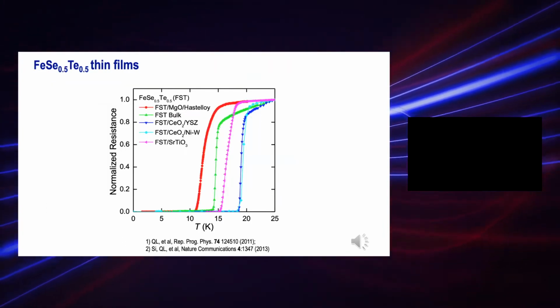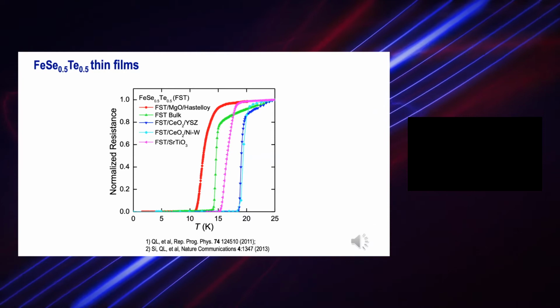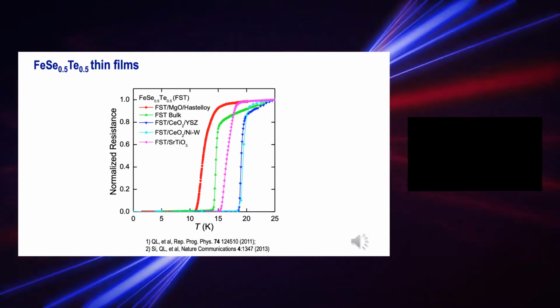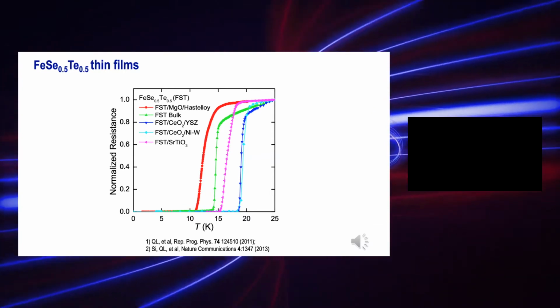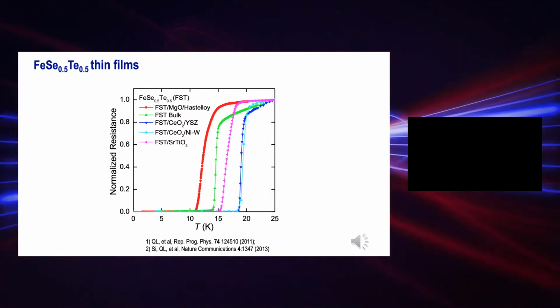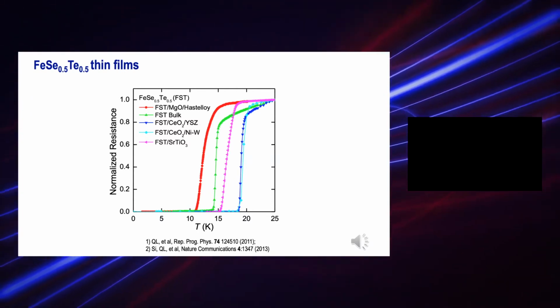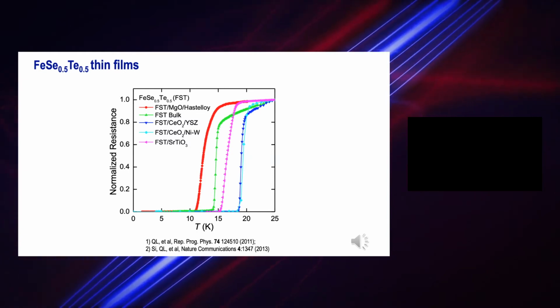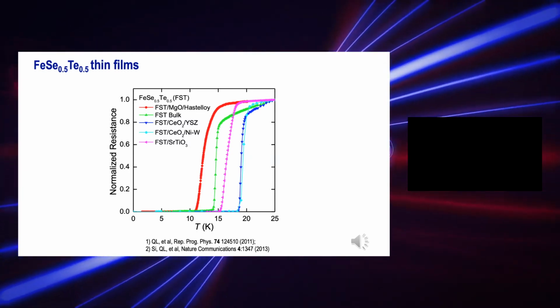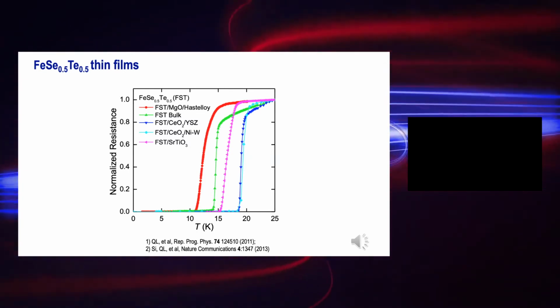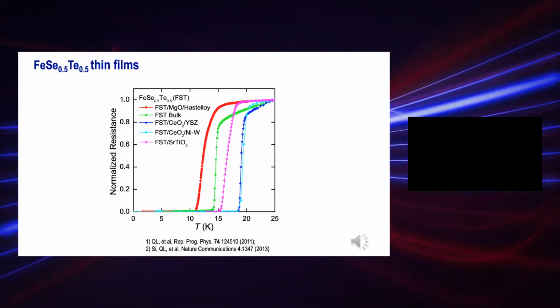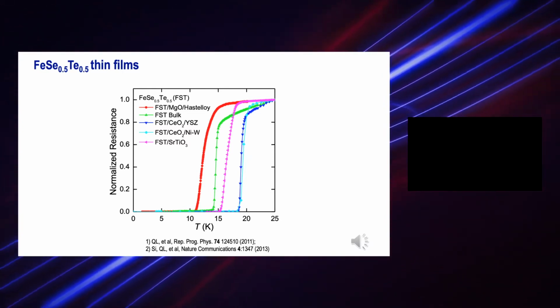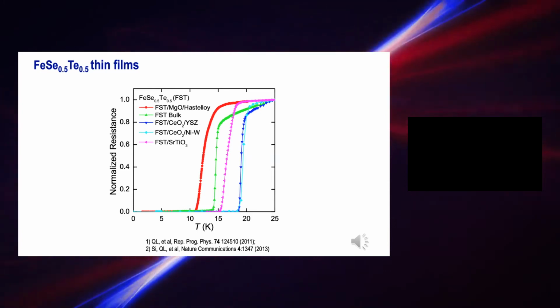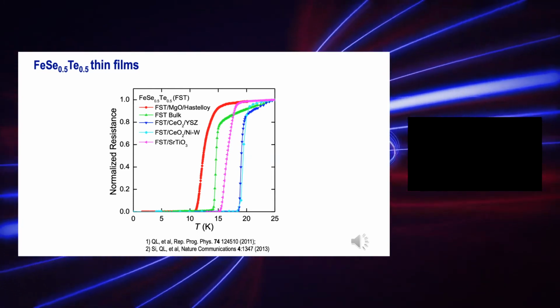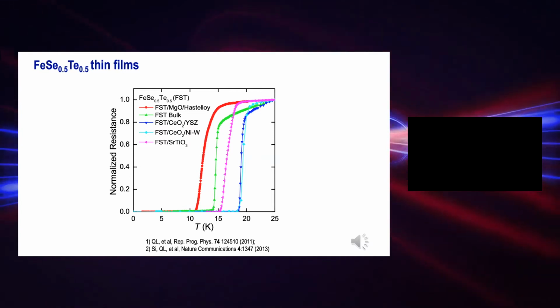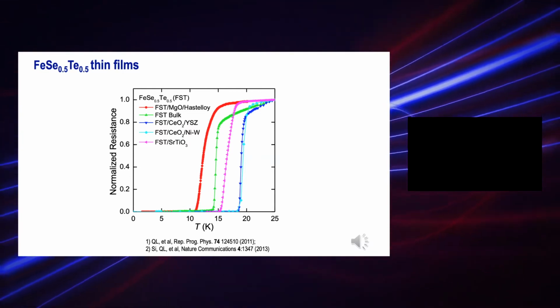In the early days, to our surprise, we found the films we made generally have a higher transition temperature than the bulk single crystals. This figure shows the normalized resistance as a function of temperature. The green symbols represent the superconducting transition of the bulk single crystals at a TC around 14.8 kelvin. The films grown with the cerium oxide clearly have a transition temperature up to 20 kelvin. That is more than 30% enhancement of TC.